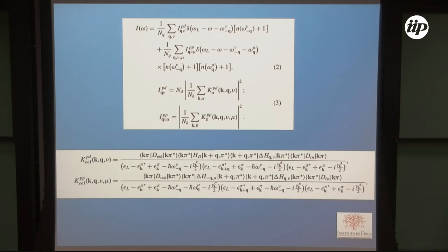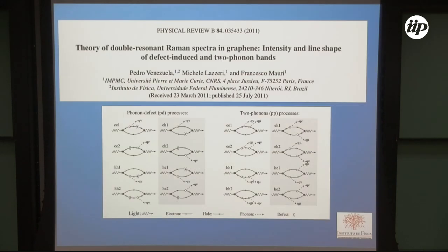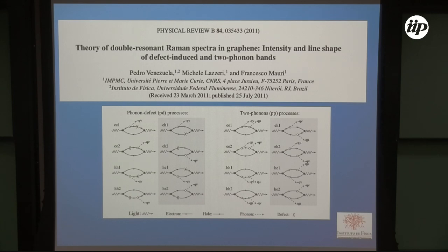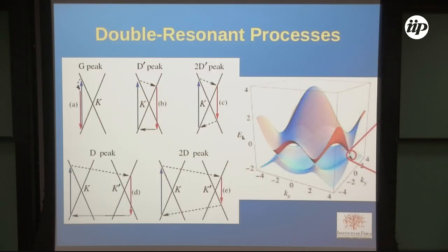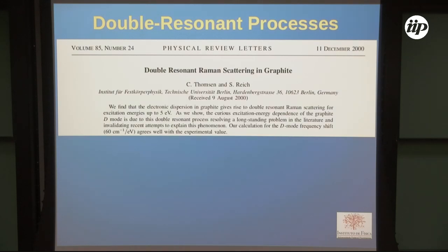We take care to have a very good description of the electronic structure, because when you do this process here, we are no longer close to the Dirac point. So we don't have linear dispersion anymore. So we did DFT calculations with many-body corrections, and then we fitted a tight binding model to this very accurate calculation. Also, we need a very good description of the phonons.